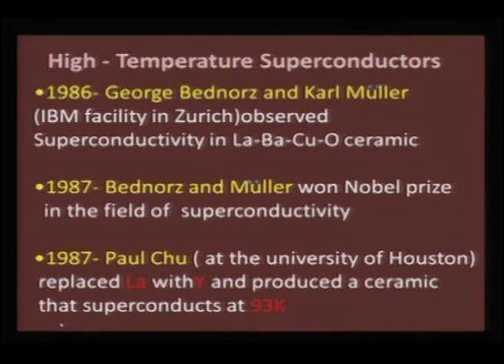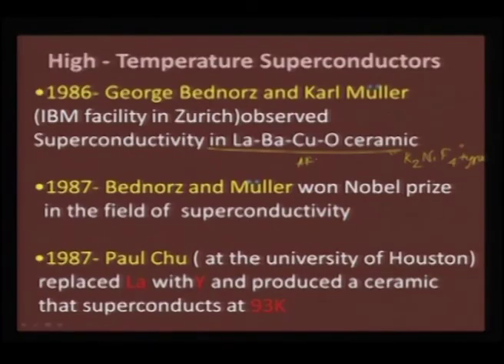So quite a good number of elements do show this strange property, but what really was the breakthrough is the high temperature superconductors. In 1986, Georg Bednorz and Karl Müller, from the IBM facility at Zurich, observed superconductivity in a compound called lanthanum barium cuprate. It is a K2NiF4 type of compound. The crystal structure resembles that of K2NiF4, and this ceramic compound is considered to be an antiferromagnetic insulator, because the copper oxygen planes interstacked in this unit cell are antiferromagnetically aligned, and the electrical conductivity shows it is an antiferromagnetic insulator.